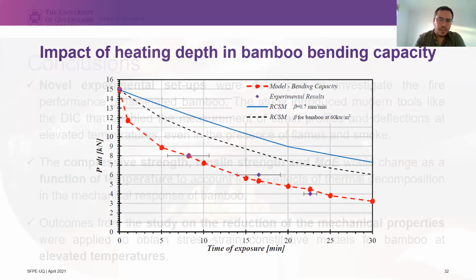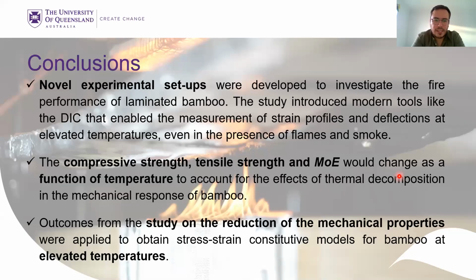So in conclusion, this study developed novel experimental setups for testing load-bearing members, or charring load-bearing members, under fire exposure, and the use of DIC was very beneficial to understand the performance of those materials. We obtained a reduction in the compressive strength, tensile strength, and modulus of elasticity for bamboo at elevated temperature, and we managed to create equations for these properties as a function of temperature.